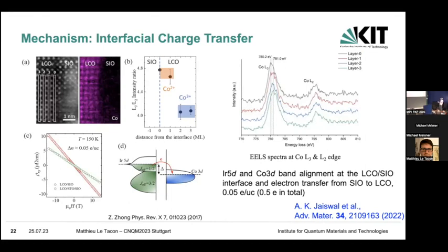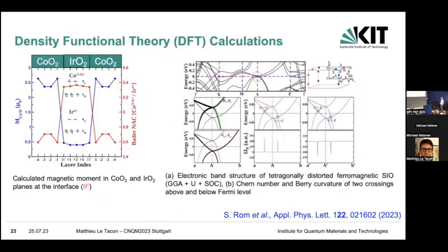But we can also do an element-resolved ILS experiment. So that's pretty much like an X-ray absorption experiment. You can look at the cobalt edge, but you can look at it with atomic resolution. And when you do that, you can basically deduce that the valence of the cobalt at the interface has changed, and it's confirmed that there is an electron transfer from the iridium to the cobalt, which is consistent also with the increase of the resistivity of the iridium layer. So there is this charge transfer.